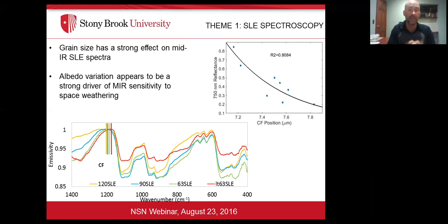So in our lab at Stony Brook, we built a machine we call PARSEC, which is the Planetary and Asteroid Regolith Spectroscopy Environmental Chamber. Within that chamber, we recreate the vacuum and temperature conditions that we see on the surface of the moon so we can acquire infrared spectra under simulated lunar conditions. This plot shows how the spectra of a mineral called pyroxene vary as a function of particle size. The yellow is 120 micron particle sizes. This is 90 microns, 63 microns, and less than 63 microns. And SLE stands for simulated lunar environment.